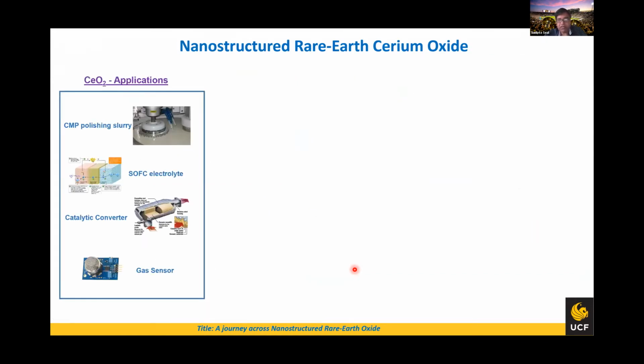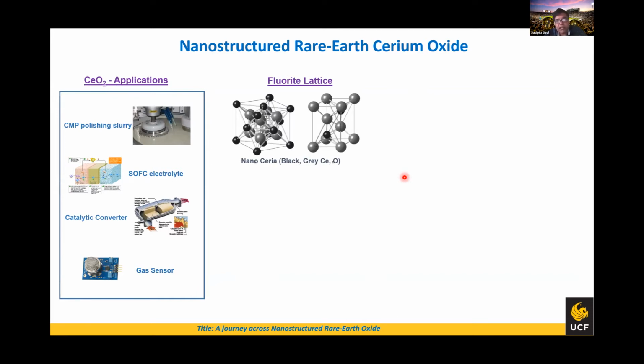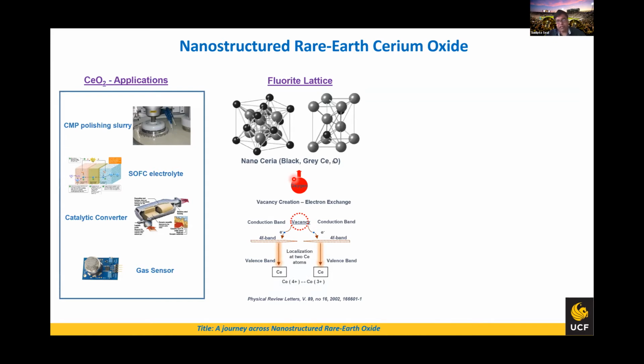What is this material? It's a material which has been used in fuel cells, catalytic converters, gas sensors, polishing slurries, and so on and so forth. This is a very industrial-scale material. But at the nanoscale, it comes in two structures: one is a fluorite structure and one is a hexagonal structure. This CeO2 is a very stable structure. But at the nanoscale, when the size goes down, oxygen leaves the surface of the material, and what happens is they leave behind 2 electrons in the 4f band, and that actually reduces cerium-4 to cerium-3.